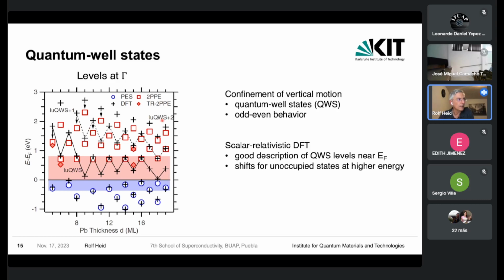Here are, for example, various measurements taken together in this diagram of electronic states at the gamma point of the surface Brillouin zone of these films, as a function of the monolayer thickness, for various different types of films collected here. And you can indeed see that if you go from, for example, 6 monolayers to 7, there is a change in these energies, and it seems to show oscillatory behavior.